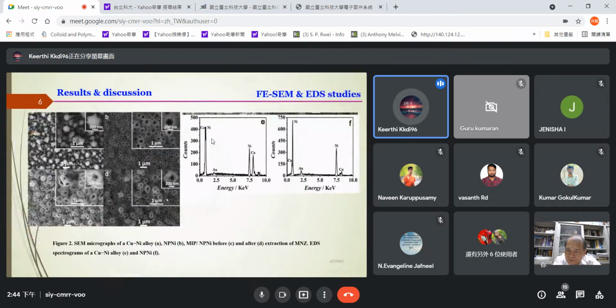Results and discussion. Figure 2a and b show the FESEM images of the copper nickel alloy. It exhibited a sheet-like structure. When the deposited copper is removed, craters and cavities form, as shown in Figure 2b. Figure 2c and d show the electrodeposited metronidazole before and after extraction. In the presence of metronidazole, the nickel balls get thicker, while when the drug is extracted from the electrode surface, the nickel balls become thinner.